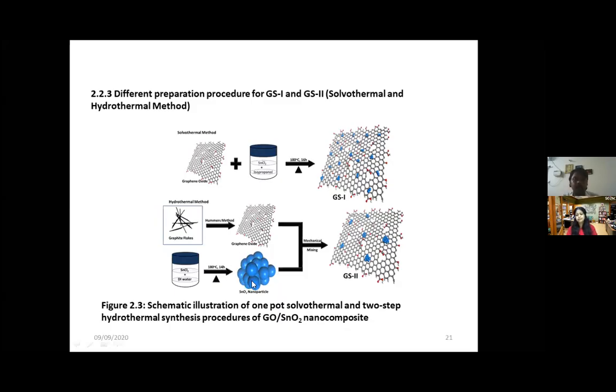We obtained a nucleated metal oxide nanoparticle here. We mechanically mixed here, in the sense that graphene oxide 100 mg and tin dioxide 20 mg are dispersed in DI water. So that is mechanical mixing. In the previous step, the tin dioxide was nucleated in the presence of graphene oxide, but here both were prepared separately and mechanically mixed. So this will be represented as GS2 from this slide.